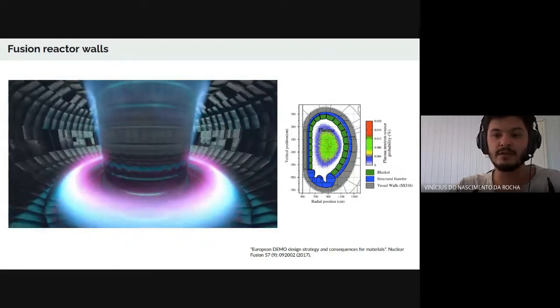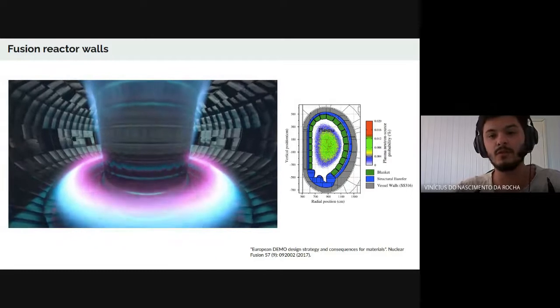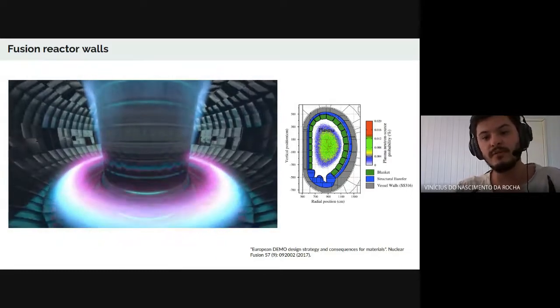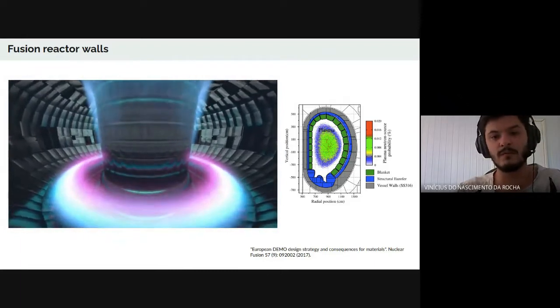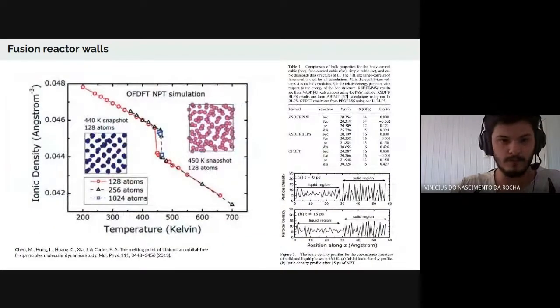Its behavior under deuterium ion bombardment has been simulated at multiple length scales to determine the conditions on which a flowing thin film will remain stable. So, DFT simulations reveal correlations between lithium and deuterium diffusivities, indicative of chemical bonding between the two. At temperatures below the melting point of liquid lithium deuteride, crystallites of lithium deuteride nucleate in the liquid, causing a step reduction in diffusivity of both lithium and deuterium.